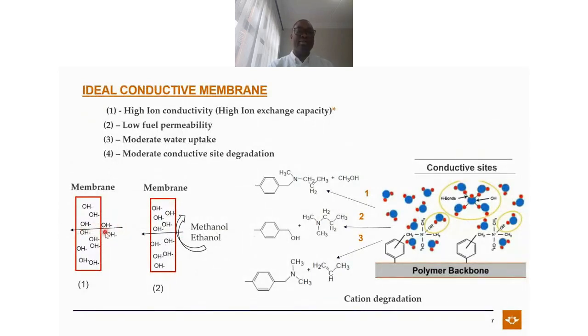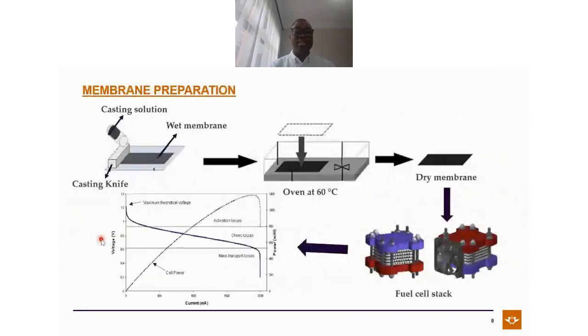So if the OH minus takes longer to pass through the membrane, that means you're going to have a high ohmic loss. If the OH passes through quickly, it means you have lesser ohmic loss, but you have higher ion conductivity. So this is related to ohmic loss. So if you have higher ion conductivity, that means this section is eliminated. But if you have low ion conductivity, this section is more, and it ends up reducing the amount of the output that you have. So since we are working on the membrane, this is the key part for us as material design for polymers or membrane in fuel cell.